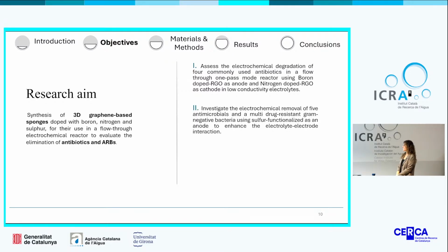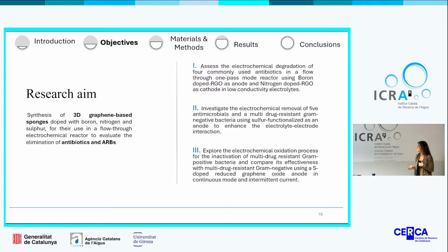In the second chapter, we investigate the electrochemical removal of 5 different antimicrobials and a multidrug-resistant gram-negative bacteria, using, in that case, a sulfur functionalization of the reduced graphene oxide to enhance the electrolyte-electrode interaction. And finally, in the third one, we explored the electrochemical oxidation process for the inactivation of a multidrug-resistant gram-positive bacteria using, again, sulfur-reduced graphene oxide, and we compare the effectiveness of this treatment with our previous investigation of the inactivation of the gram-negative bacteria.